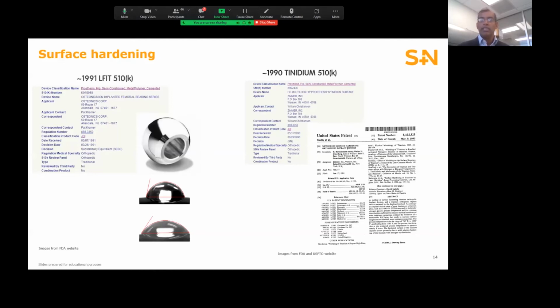Nonetheless, over the years, a number of surface hardened materials have been developed to avoid the risk of fracture. This slide displays two of them. The first is LFIT, which is a hardened cobalt chrome material. It's created through a high energy process that's used to impregnate nitrogen into the surface. It's been marketed in part based on claims of reduced friction and improved wettability, which can be quantified by the measurements of contact angle. In fact, LFIT is an acronym for low friction ion treated.